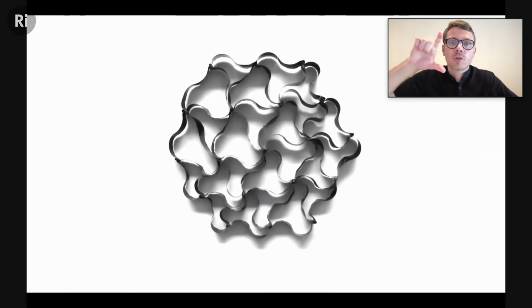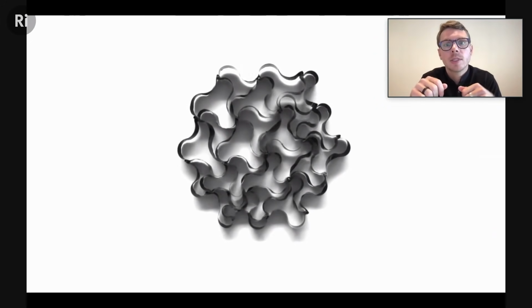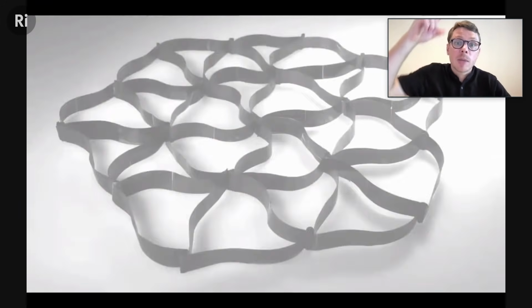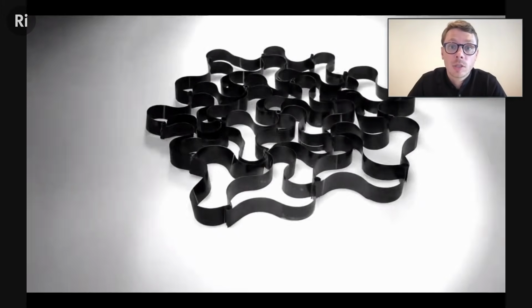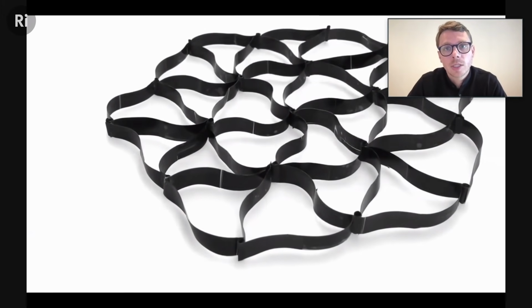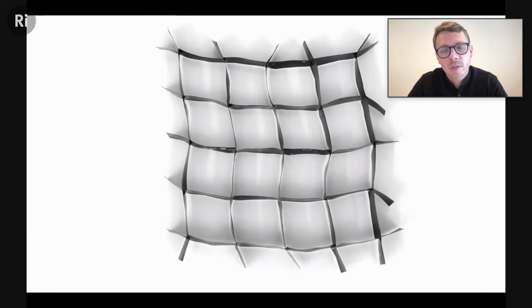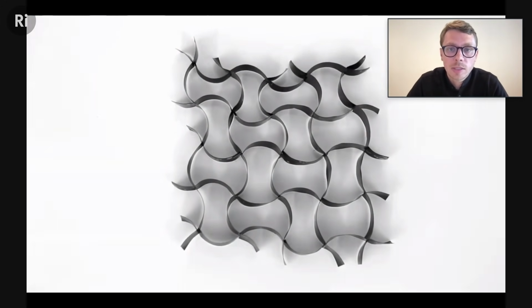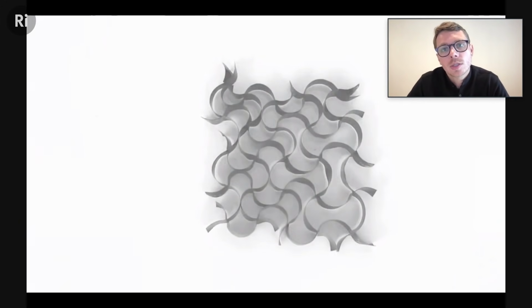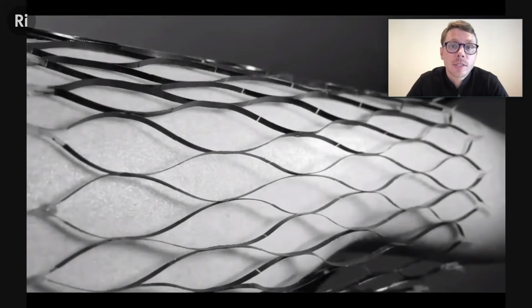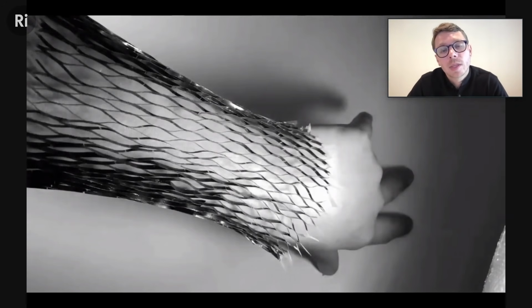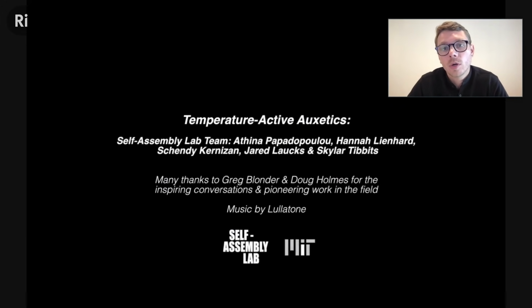In this case, it's something called auxetic. So typically when you have a material and you stretch it, it'll shrink in the other dimension. Auxetic materials do the opposite. When you stretch it, it expands, or when you compress it, it compresses uniformly in all dimensions. And that's a really fascinating phenomenon, and we can create that with these materials. So auxetic structures that transform based on temperature change or sunlight. And this was the beginning of our work to construct our own textile.